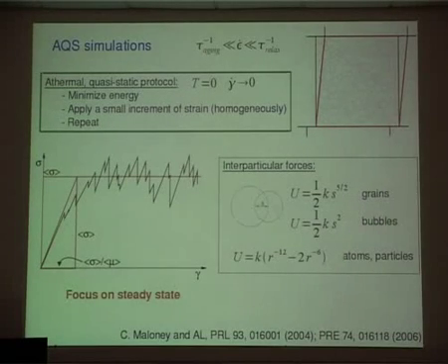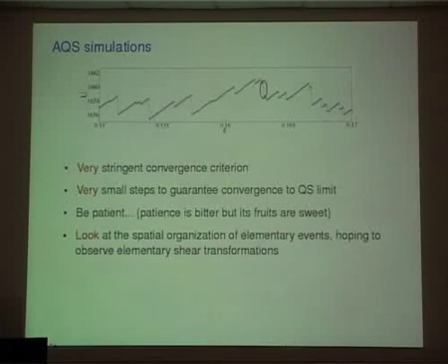And it is symmetric also here, but with a slight shift. This shift increases, and by increasing the shift, we introduce strain in the system. We introduce strain in a way which is translationally invariant, and that's a way to avoid a lot of boundary effects that would be found in experiments. Just for the sake of completeness, we've used a variety of potential interactions. I'll show you data mostly with Lennard-Jones systems.